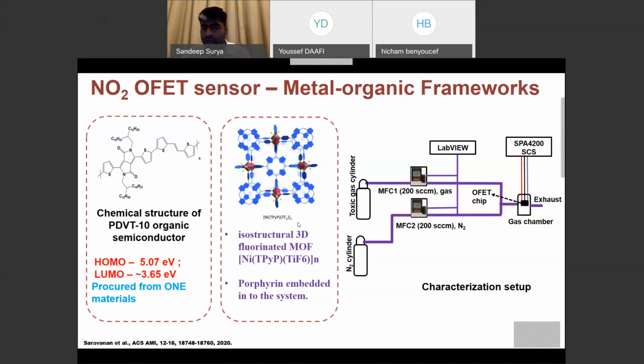For the first time, we used an isostructural 3D fluorinated metal organic framework with porphyrin inside. If you remember, in my very first experiment related to explosives, we used copper tetraporphyrin. There, the copper porphyrin was used as the receptor layer alone. Here, in this case, there is a synergistic combination of both MOF and porphyrin, wherein the porphyrin was made use of as the organic ligand that is present in the structure of the MOF material.